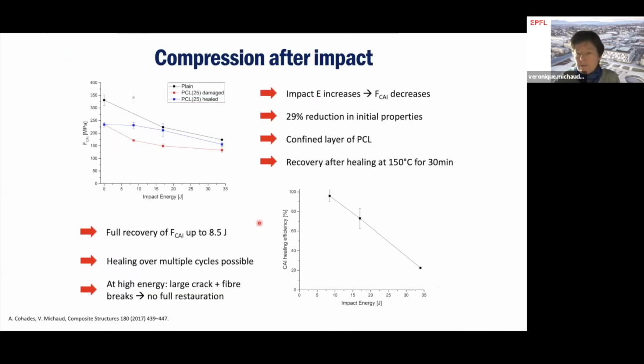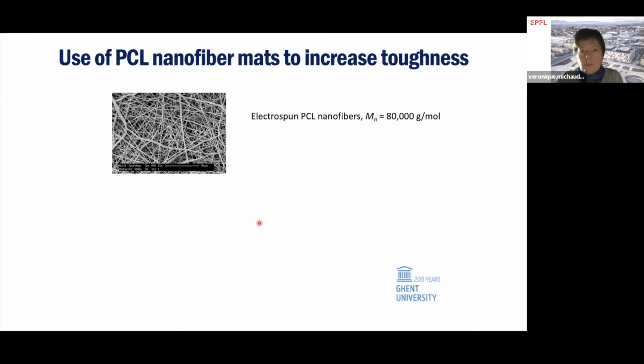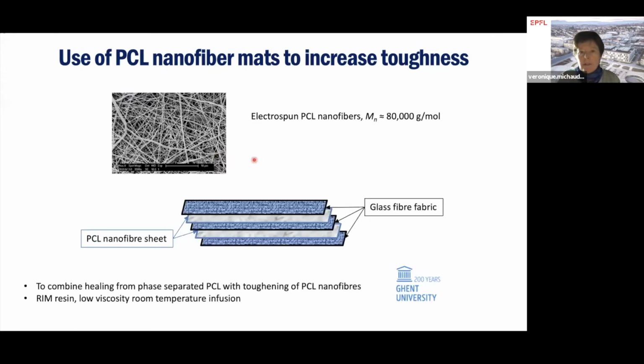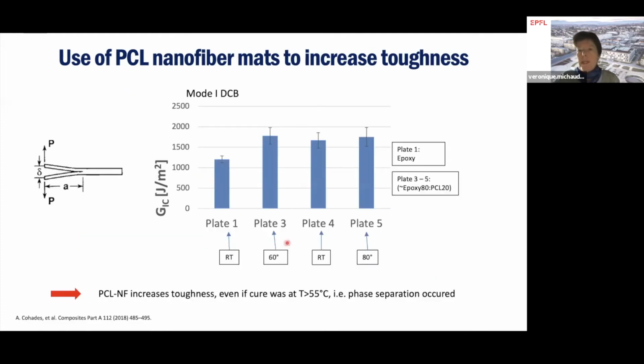So to increase the toughness, because this is really the Achilles heel of that PCL material, we considered the use of nanofiber mats. This was a collaboration we had with colleagues from Ghent University, where they make electrospun PCL nanofibers, which we integrated into the composite with one PCL nanofiber mat between glass fiber fabrics. Then we impregnated with an epoxy resin, we cured, and we looked at the properties. We used different ways of curing the material, and then we did some DCB testing to look at the toughness